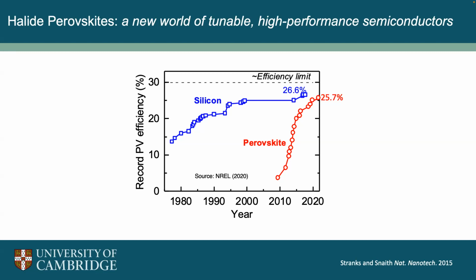where, as I showed in the previous slide, we're taught we have to make a semiconductor very, very perfectly crystalline, with no defects, to make it perform well. And this material is actually rewriting that a bit. In fact, in many ways, some of the more disordered versions of these perovskites actually perform better than the more ordered versions. So it's very interesting from a technological point of view, but also from a scientific point of view, that we're seeing this new class of materials that rips up the textbook in many ways.